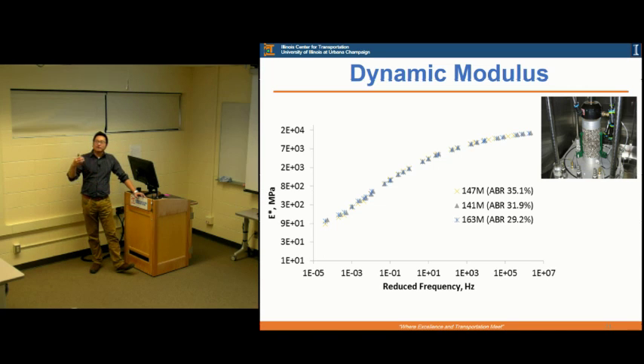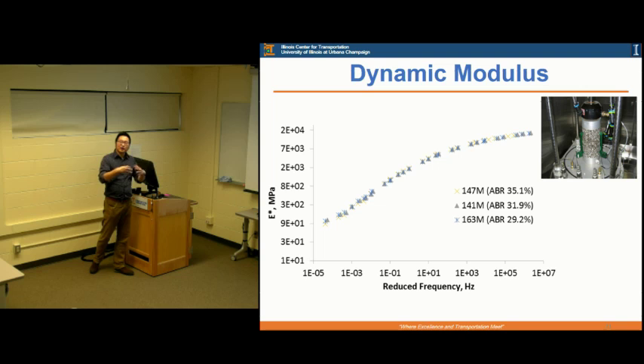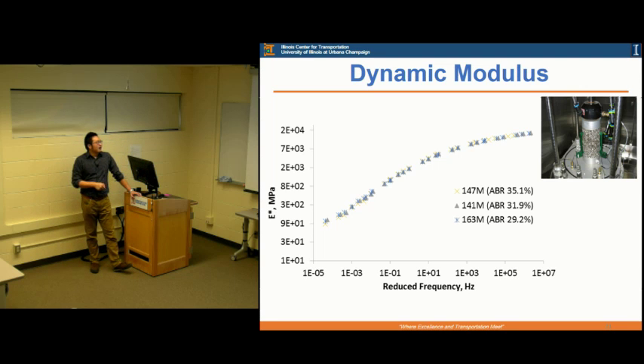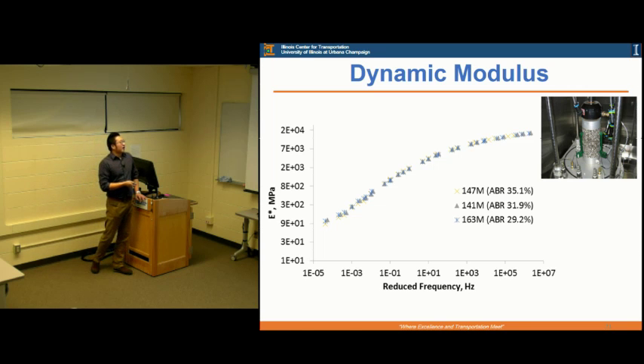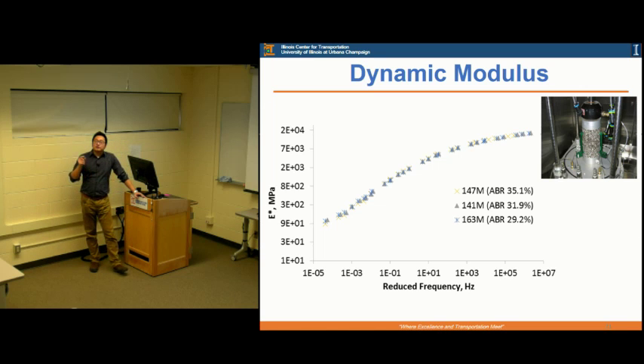So you have a lot of values at different temperature and different frequency, and you are trying to convert into the master curve, so you want to compare them over a wide range of frequency. In this case, they are very close to each other, overlapping, because all the mixes are very similar in aggregate gradation. Even though you have a different ABR, it's very hard to use the E star test to distinguish all the mixes. Also, E star just focuses on the non-destructive range, so you barely can see that difference just using the E star.